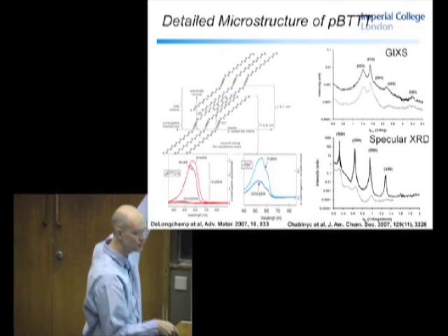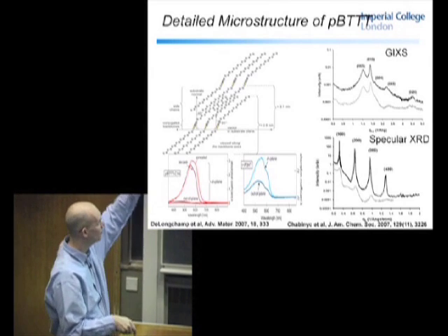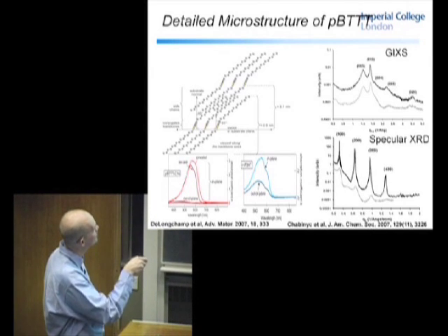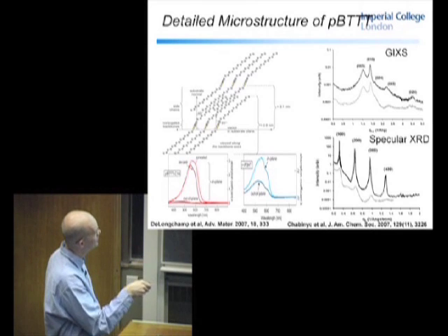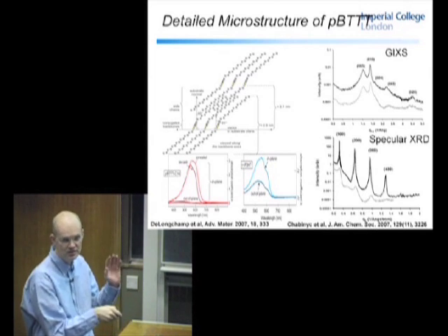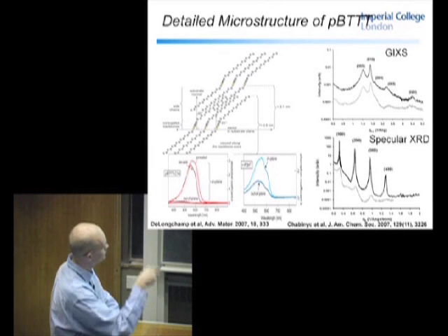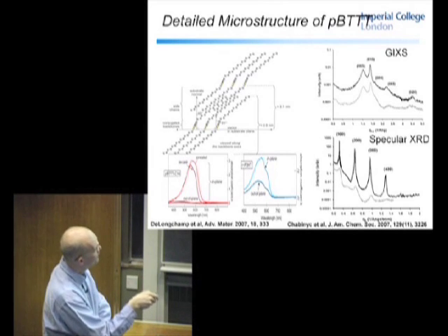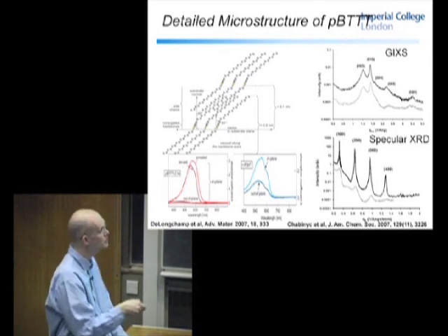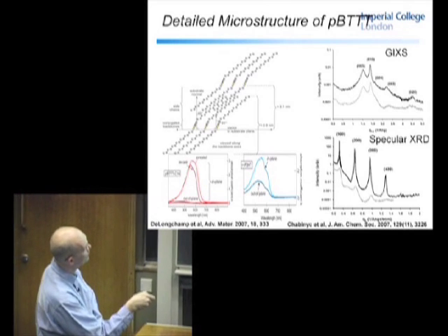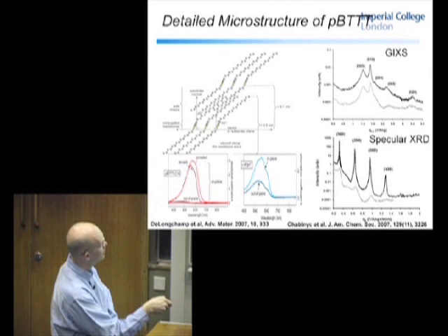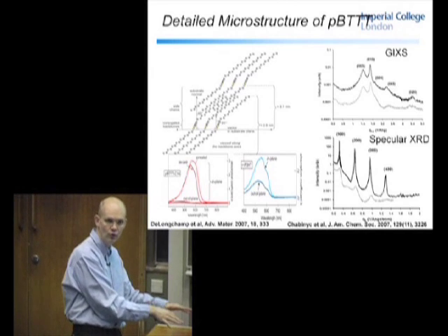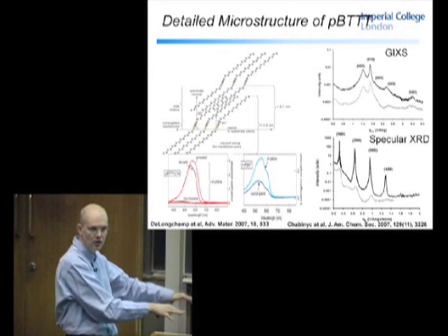Specular X-ray diffraction is the opposite. You're coming in more or less out of plane to the film, so you're probing the distance between the lamella, the D spacing if you like, and you can see this is a 1-0-0 reflection, again very sharp. And you see higher order reflections. Again, this is indicative of a highly crystalline film. And the fact that there's no mixing here between the out of plane and the in plane reflections, so in other words, there's no 1-0-0 reflection in the in plane, and there's no 0-1-0 out of plane, shows that these lamella are also very well oriented, so there's no sort of misorientation of the domains.